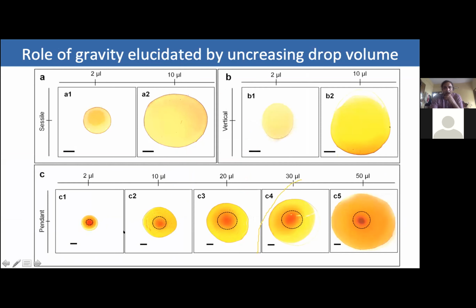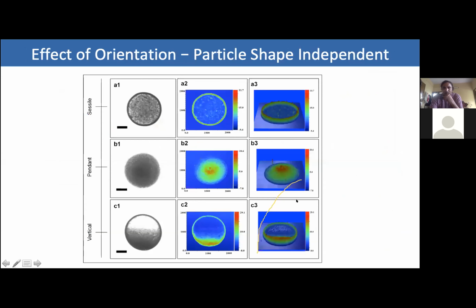So we've looked at the effect of drop volume here. So this is a sessile case and the vertical case and a pendant drop case. You will see that the intensity of the central deposit increases with the increase in the drop volume. Again, shows that the gravity effect becomes important when you have larger droplets. And we have also shown that this also occurs independent of the particle shape as well.